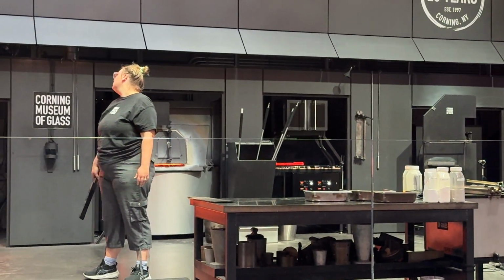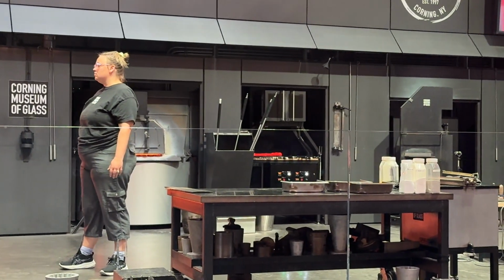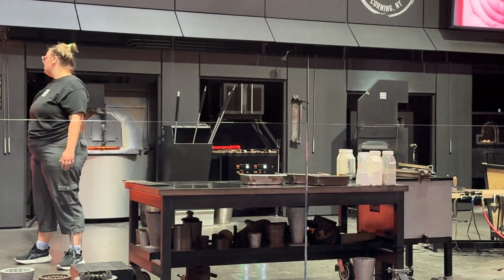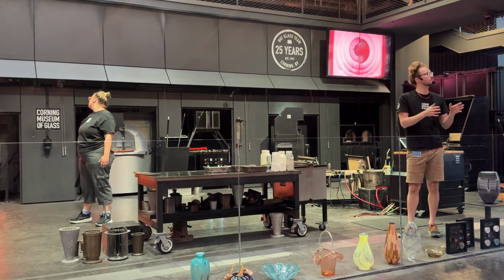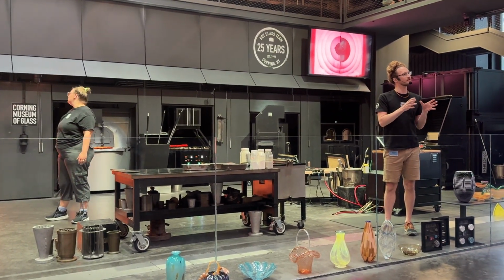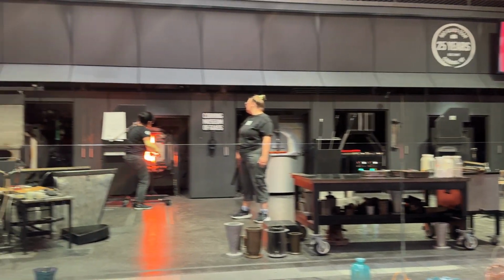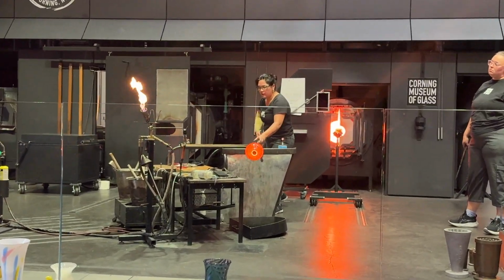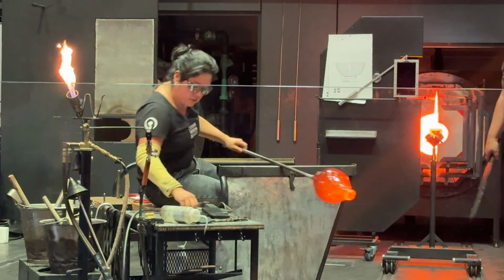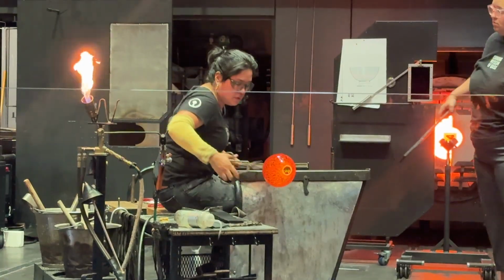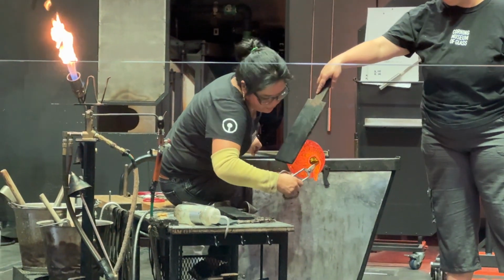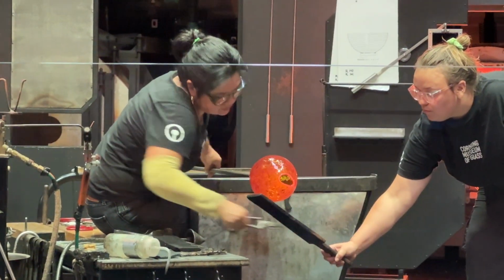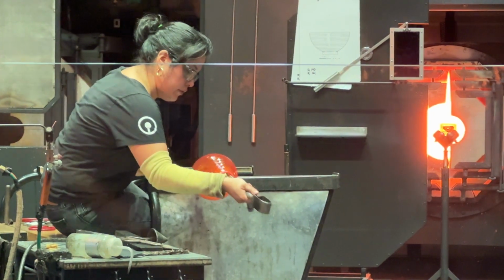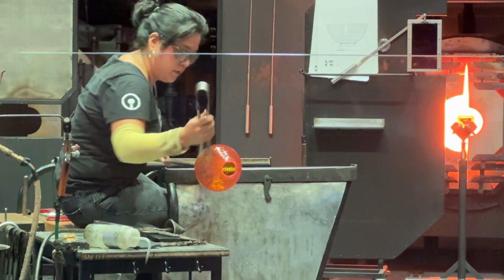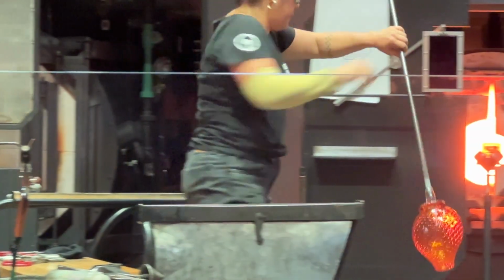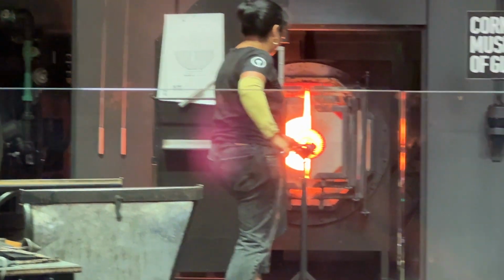We don't typically use wood at that point because we can embed wood ash into the glass; the wood can actually stick. So we'll use metal or graphite. As the glass cools though, we'll switch to the wood tool because it's a little softer and it's not going to pull as much heat out as quickly. So we use the wood paddles to flatten the forms, but this one's all burnt up. It says shield only, so you're not supposed to use these ones to shape glass, but clearly it's burnt. We'll sometimes use this to put in between the glass maker and the glass, just to shield them from some of the heat that's being radiated off of that piece. But yeah, so we use them for shaping and shielding.